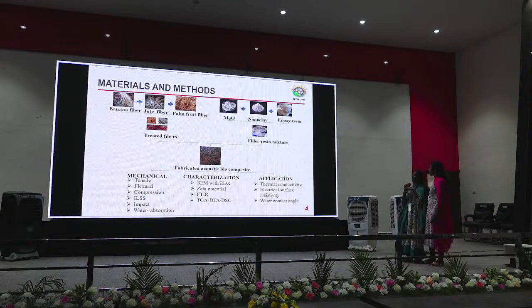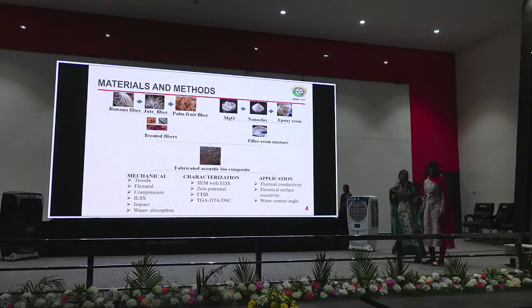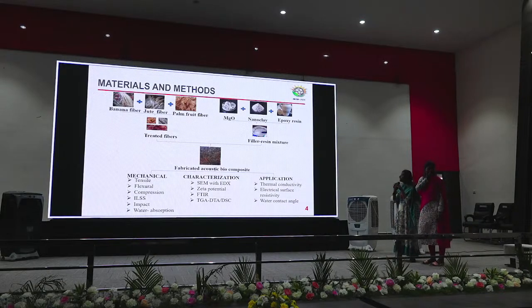This is the materials and method. First we collect the raw fibers, then chop them into the required shapes. Later they are treated through alkaline treatment in 5% NaOH. MgO and nanoclay, which are fillers, is mixed with the epoxy resin to make the filler resin mixture. Using a hot press compression mold, we spread the chopped alkaline-treated fibers in the mold and pour the filler resin mixture in, then compress at 1500 PSI for an hour. Later it is post-treated and we get the fabricated acoustic biocomposite material.